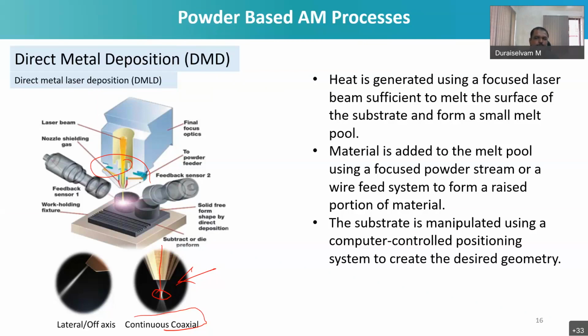So here heat is generated using a focused laser beam that is sufficient to melt the surface of the substrate to form a small melt pool, and the material is added to the melt pool using a focused powder stream or a wire feed. Here rather than using a powder, you can use a wire feeding system also, and you can manipulate the substrate like that. Here you can see that you build a kind of cylindrical material one by one, layer by layer, and you can realize the final product. So likewise, you form one layer over another like this continuously, and you can build the entire material for the system.